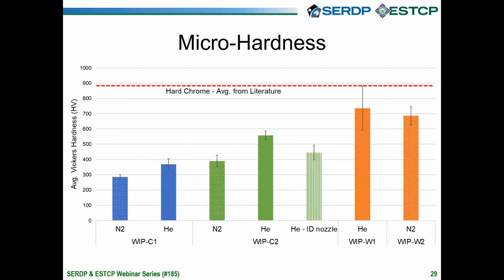Next is micro hardness. So there's some trends that we can observe in the micro hardness data. First, the feedstock material has a significant effect on the resulting hardness of the deposit. So we saw that C1 has the lowest average hardness, C2 has something in the middle, and W1 and W2 have the highest overall hardness. We can also see that there's a difference in hardness between the helium and nitrogen versions of each feedstock. So we typically see the helium version is slightly higher hardness than the nitrogen version. But that's of secondary importance to the feedstock itself.